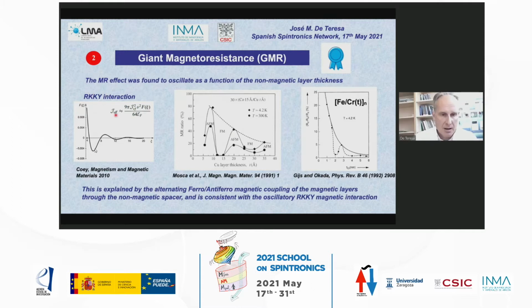This is an interaction which was known at that time between magnetic impurities in a metal. Depending on the distance between these impurities, it was observed that the exchange interaction, the sign of the exchange interaction, was oscillating with the distance. So it has this dependence with this formula. And this is related to the Friedel charge oscillations of a magnetic impurity in a metal. Good. So can we do the same thing with the multilayers?